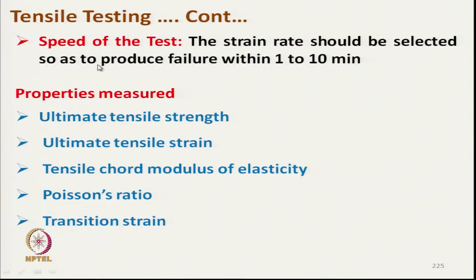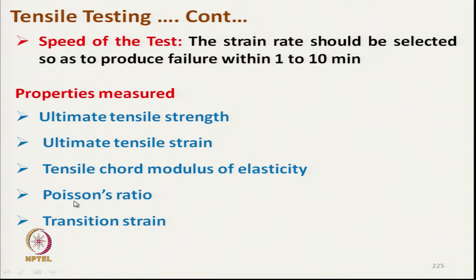As per the standard, the strain rate should be selected to produce failure within 1 to 10 minutes. Properties that can be measured include ultimate tensile strength, tensile chord modulus of elasticity, Poisson's ratio, and transition strain.